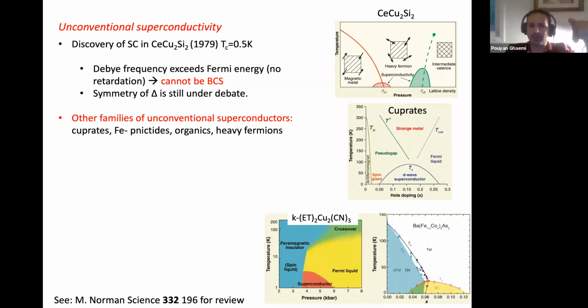Onur, just a quick question. Is it only in this compound, or in many other families, that it's also questioned whether they are D-wave? I think for cuprates, people agree it's D-wave. In heavy fermions, usually the gap is much smaller. So if your TC is half a Kelvin, and you look at some experimental probe like ARPES or specific heat, D-wave superconductors would always have a V-shaped density of states, which you can deduce from the temperature dependence of these probes. But in cerium copper 2 silicon 2, it looks like D-wave, but at very low temperatures, close to zero temperature, it becomes fully gapped. Okay, thank you. So it's not really clear.